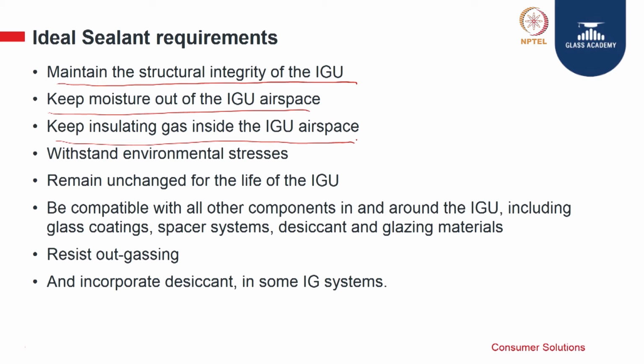And what is also important to understand is that when you apply the sealant, primary or secondary, it gets bonded to different materials. It gets bonded to the metal spacer, to the glass coating, and to other accessory materials like the spacer and glazing materials. Sometimes the weather seal comes in contact with that. So, what we essentially need to understand is that this should be compatible. The materials which come in contact with the sealants should all be checked for compatibility prior to use, and resist outgassing.